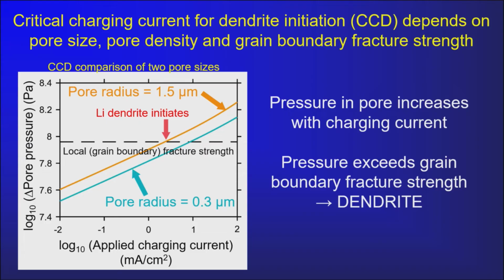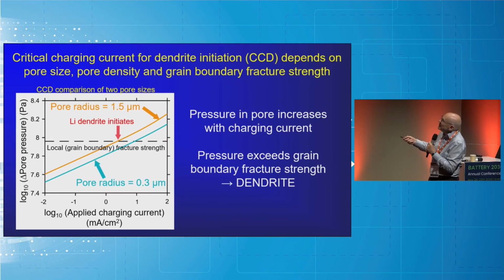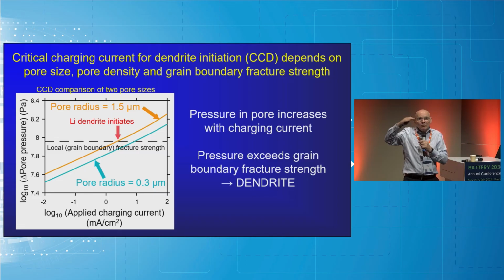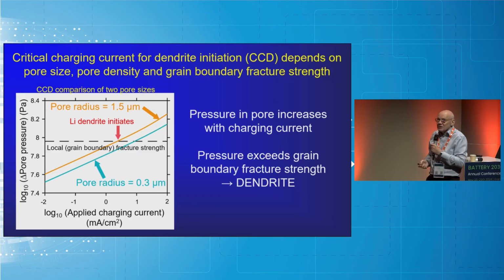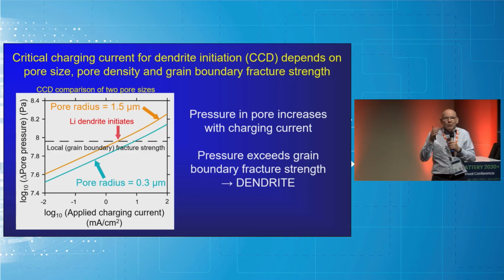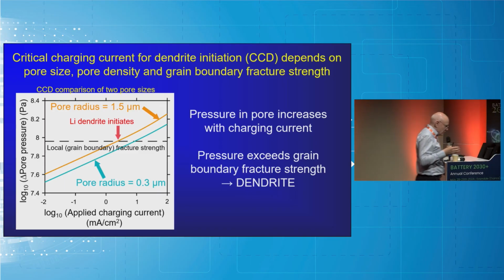And this is done for two different pore sizes. This one is actually effectively no pore because it's the same radius as the crack, and this is for a pore with a 1.5 micron radius. And the point here is you can see that the pore makes things worse. The pore is the weak link. The pore means that you can only get to a lower current density and then a crack. You want to get to the highest current density possible without cracking. Pores make things worse. Now, pores are the weak links. That's where the cracking process starts.